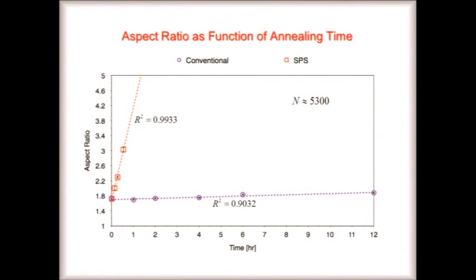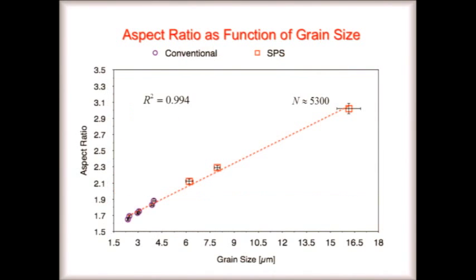And I looked at this, and I didn't understand anything. And I thought, OK, because I'm stupid, and I'm comparing this as a function of time, and we shouldn't be doing that. We should be looking at aspect ratio as a function of grain size. And when you do that, then, of course, the SPS data is up here, and the conventional data is down here, but it all fits along one line. But this should also bother us, right? Because this can't be.